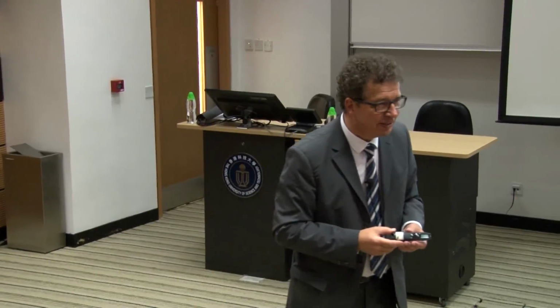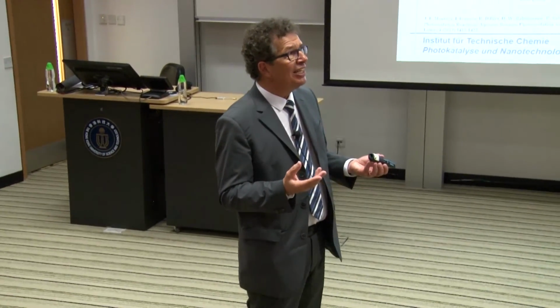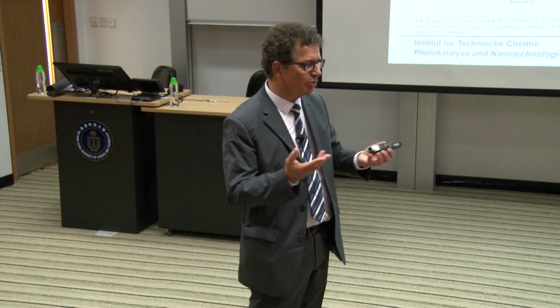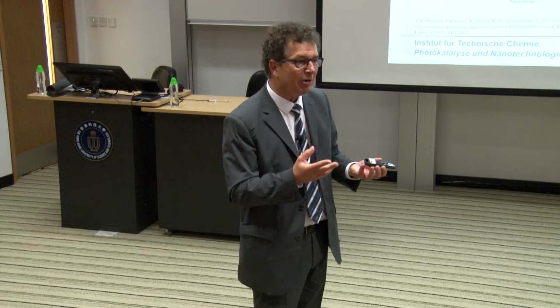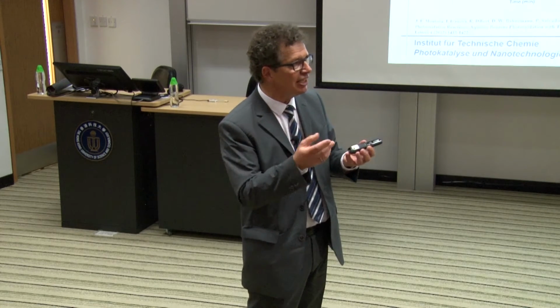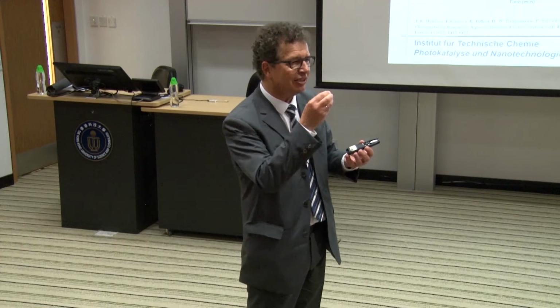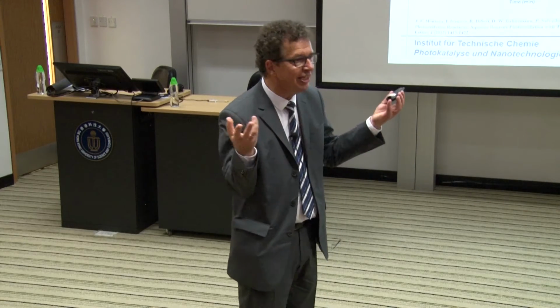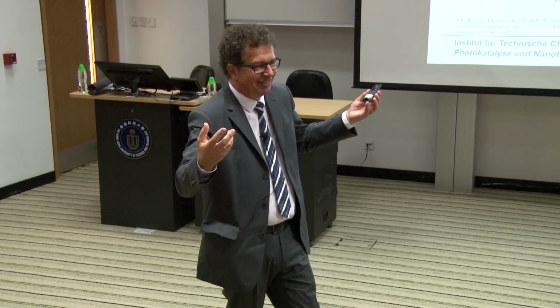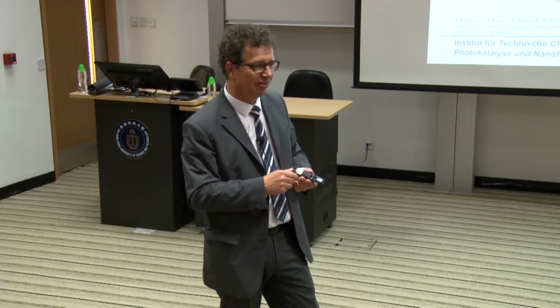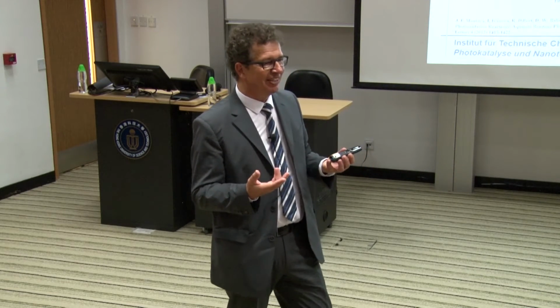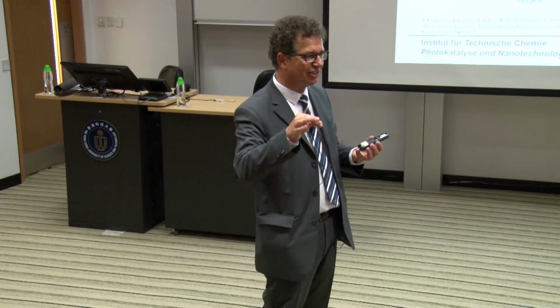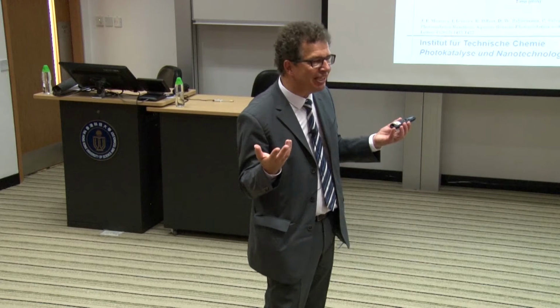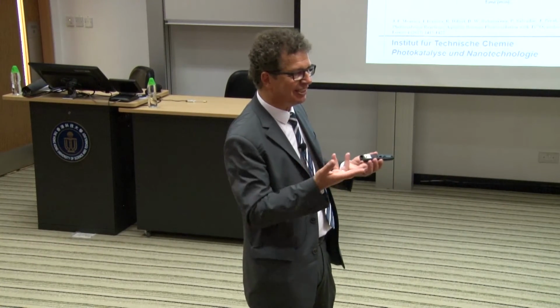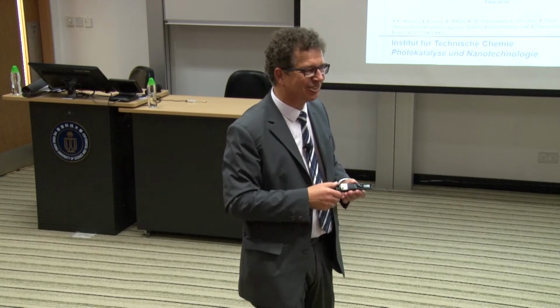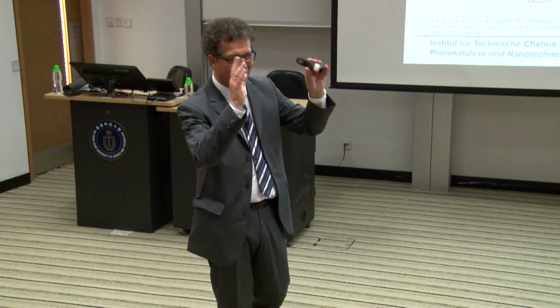So how big is the metal size, the cluster size? A little smaller than our TiO2 size, so we're talking about 2, 3, 4 nanometers in diameter. But that is pretty big, imagining that you usually take less than an atom percent of your metal, which means you really cannot have a metal contact at each semiconductor particle because the amount of metal you put in is very small. It would be a disaster if you needed a contact at each nanoparticle in the ensemble, because then you would need as many metal particles as TiO2 particles, and this costs you 100 times as much as the TiO2, right? Even if you take just silver, not talking about gold or platinum or something like that.